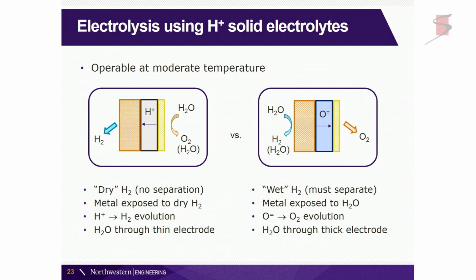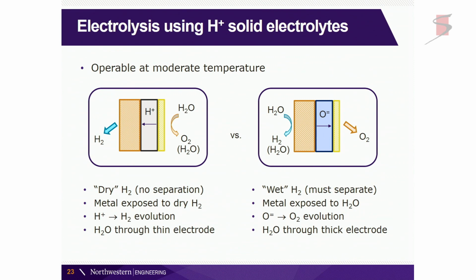But if I compare these two systems, there are some intriguing differences. First of all, this electrode, this is the fuel electrode, where I showed you we have nickel as the electrocatalyst, and this whole thing is our thick electrode because it is the piece that is providing the mechanical support to this 20 or so micron thin membrane. And so this is a lot of nickel that's here, and we are basically removing hydrogen from this nickel side. We are supplying steam to the mixed conducting oxide electrode, which I'll just call the air electrode because it's operating as an anode in the electrolysis mode.